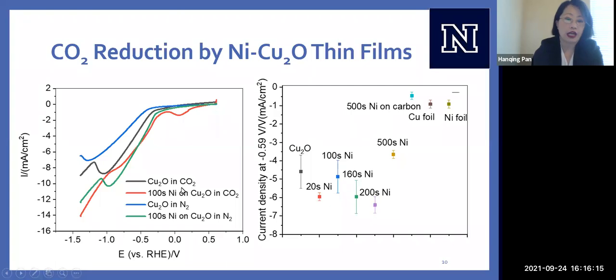So we've looked at this reaction in 2 different gases, CO2 and nitrogen, just to confirm that CO2 reduction reaction indeed is happening. And there is definitely more current density when it's in CO2 than nitrogen. We can also arbitrarily pick any voltage and look at all the different catalysts and look at all the current densities that they're generating. And so at minus 0.6 volts, the catalyst that is generating the most current density is the catalyst with 200 seconds of nickel electrode deposition.